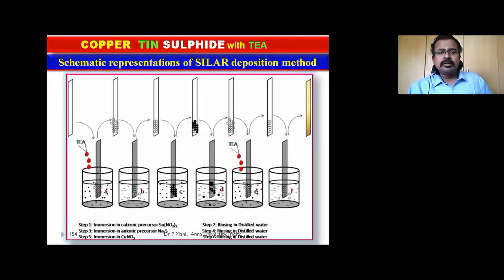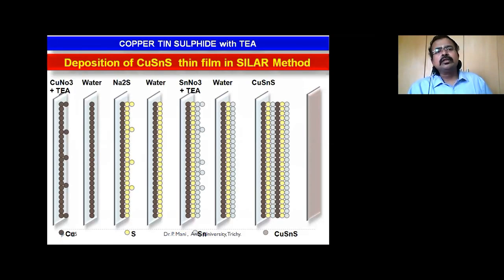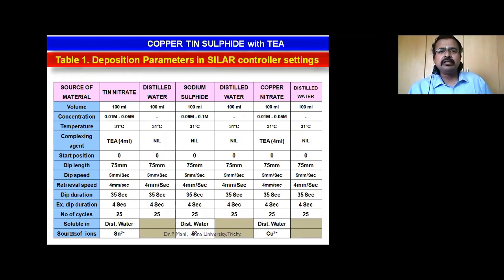Now we are seeing the experimental setup. For 3 elements, we are having 3 different beakers. In between the beakers, we are having deionized water to rinse, and this was deposited copper nitrate plus TEA in the first beaker, then water, sodium sulfide in the next beaker, water next, then tin nitrate and TEA, then water. Finally, we are getting copper tin sulfide. So these are the deposition parameters.